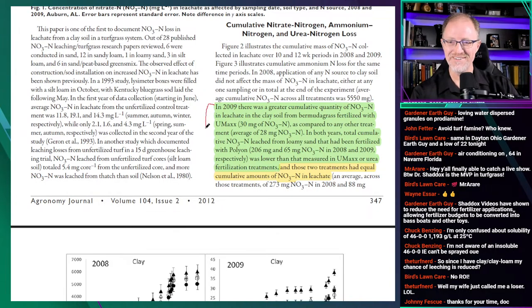Jesus Christ, it's unbelievable. As compared to any other treatment, in both years, total cumulative nitrate leached from loamy sand that had been fertilized with Polyon was lower than that measured in UMaxx or urea fertilized treatments. So that's pretty consistent too. Polymer coated urea, and any slow release generally, will reduce leaching compared to solubles.